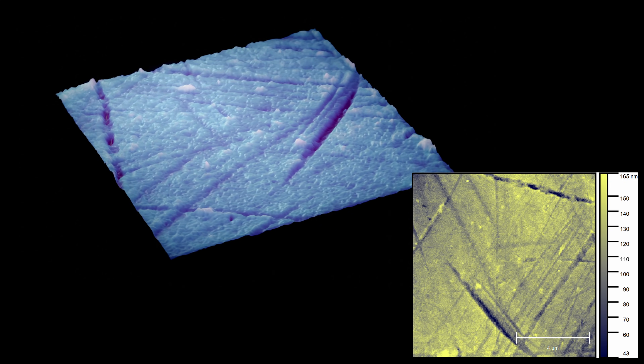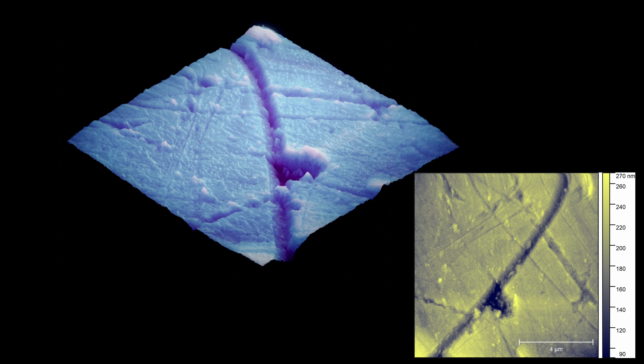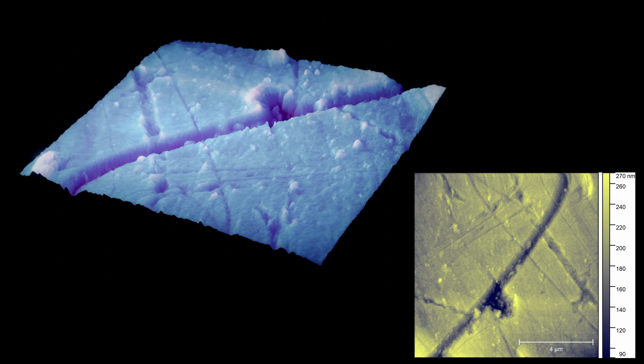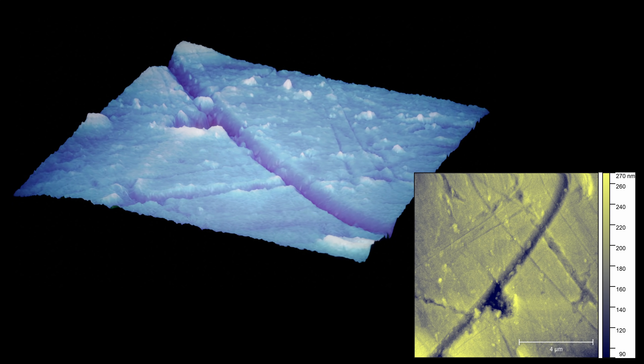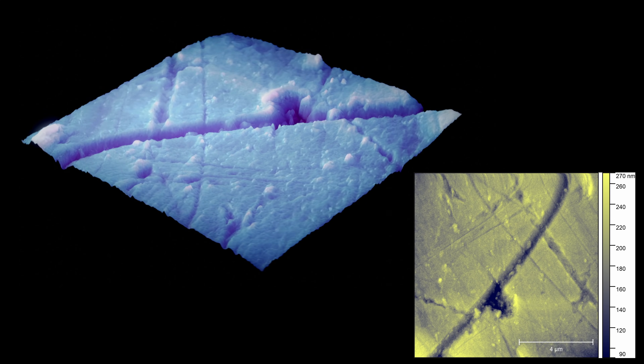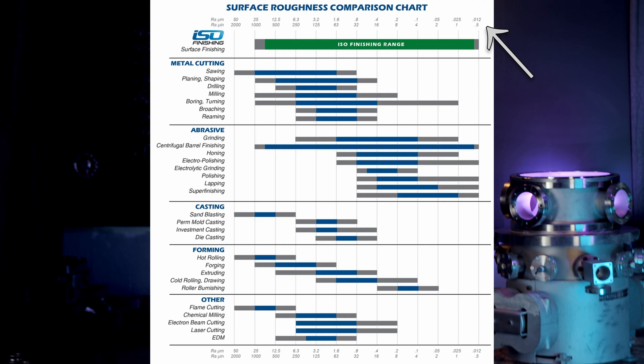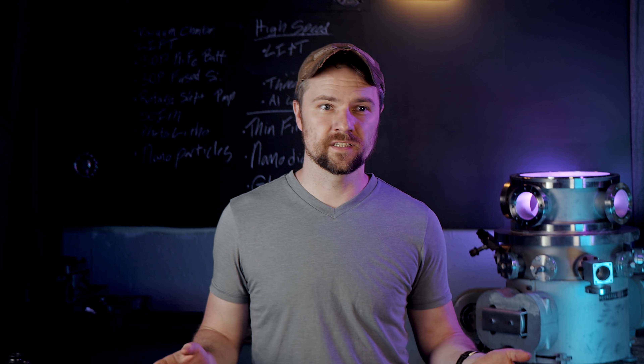It's very cool and also surprisingly flat. You can see grinding marks similar to what we saw in the gauge block. The large scratches are 500 to 700 nanometers wide, with the smaller ones being anywhere from 50 to 200 nanometers, and pretty shallow. The deepest pit or scratch was 130 nanometers on average, and the tallest peak was about 200 nanometers above the average surface. The surface roughness was only 12 to 18 nanometers, which is really impressive — that gives it an N1 on the ISO grinding surface finish scale, which is very, very flat.